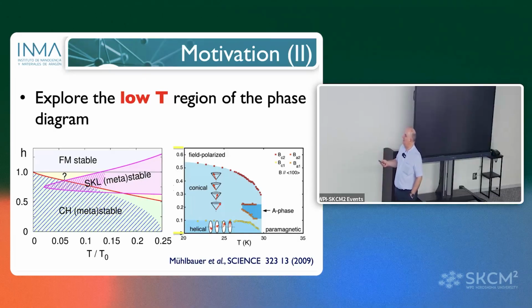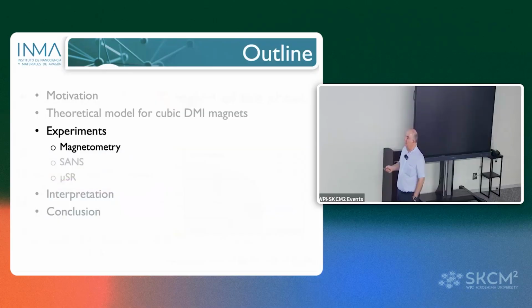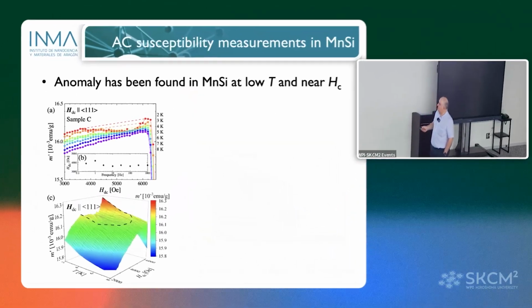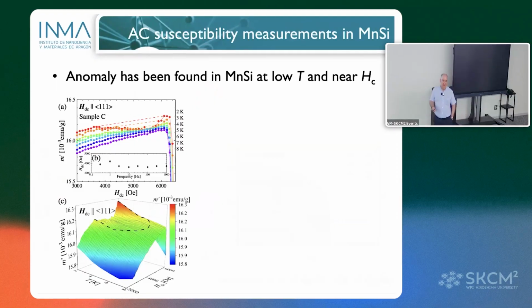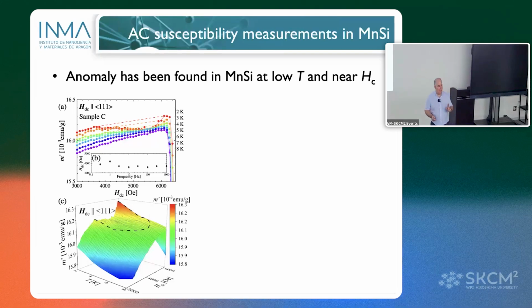Let's explore the low temperature area in the phase diagram, and do magnetometry experiments, small angle scattering, and muon spin rotation. We fabricated 3 different samples, and we oriented each sample. We know for each sample the A axis, B axis, and C axis, and also the 111 direction, the 110, etc. We know all the main directions. Then we measure by applying the magnetic field parallel to 111. This is called sample C.